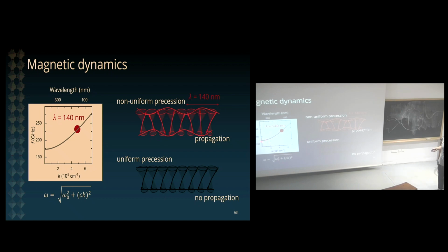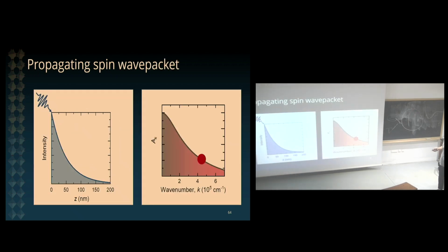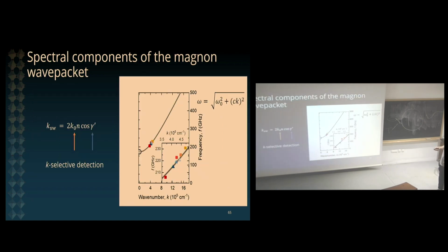Okay. So while the low frequency corresponds to this uniform mode at k equals 0. So that's the key message here: by confining the excitation over a sub-wavelength slab at the surface of your material, you're exciting a certain number of Fourier components of a propagating wave packet, and we can probe specific ones by changing the experimental geometry.